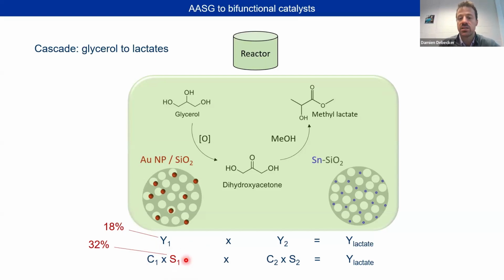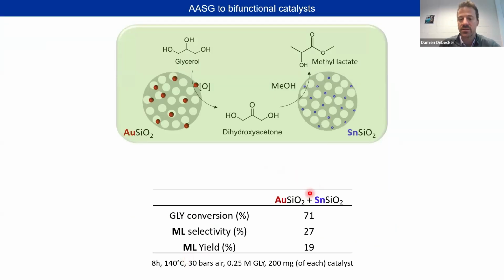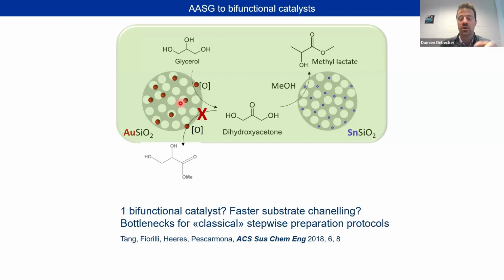first catalyst. And indeed, this is exactly what we observe if we just mix the two catalysts as a mechanical mixture and we put them in the reaction. We also have a selectivity that is about 30% and a yield that is about 20. So same problem, actually, we keep having this problem of over-oxidation on the gold catalyst. So how to solve it? Well, maybe by putting the two active species together on the same solid so that the path between the two active phases, active sites, this one and then the tin one, would be shorter, and you have a better chance for this intermediate to go towards the final product.